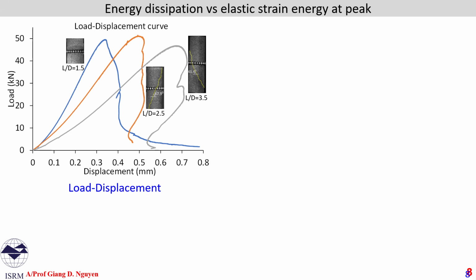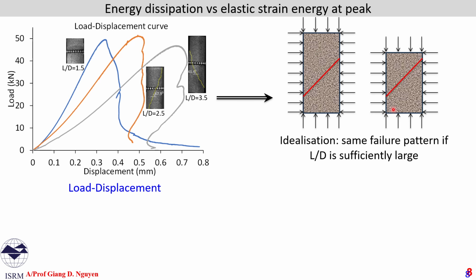We go one step further to look at energy dissipation. I represent here the load displacement curves of these three specimens, and under idealized conditions, the two specimens with length to diameter ratio of 2.5 and 3.5 have roughly very close shear band angles. Ideally, under the same stress conditions and the same material, this shear band angle should be the same, and it is the case when the length to diameter ratio is large enough. So we consider these two cases here as an example.